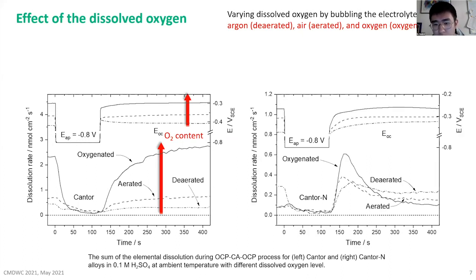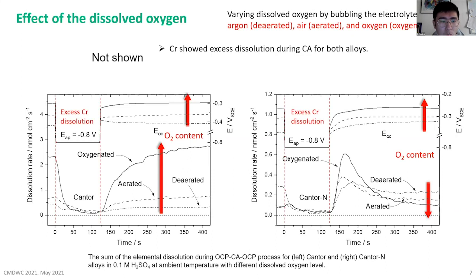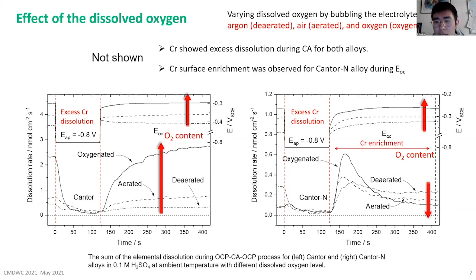And on the right-hand side, we show the results for the Cantor N alloy. We can observe inverse results for the Cantor N alloy. When we increase the dissolved oxygen content in the solution, we observed a decreased dissolution rate for the Cantor N alloy, although similarly we observed the increased open circuit potential. And what is not shown in this figure is that we observed excess chromium dissolution during the cathodic activation. And for the Cantor N alloy, we observed chromium enrichment during the spontaneous passivation process. This implies that even for such a complex alloy with 5 elements, chromium was still the major component that contributes to the passivation.